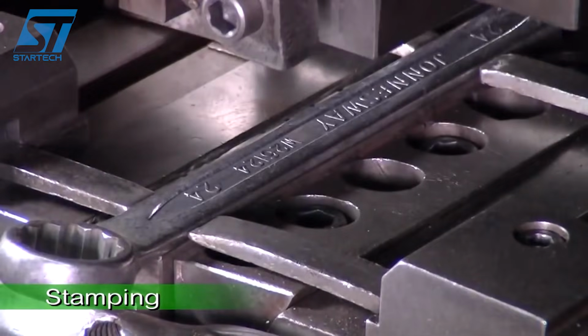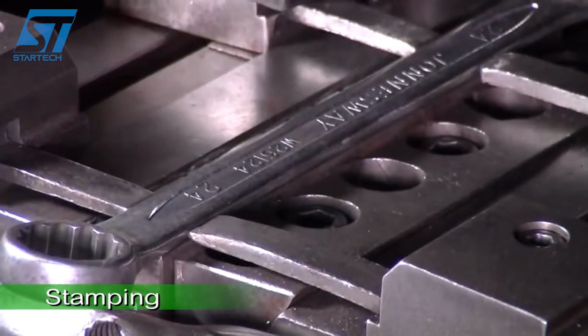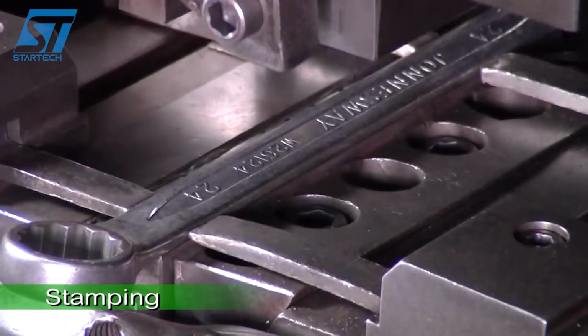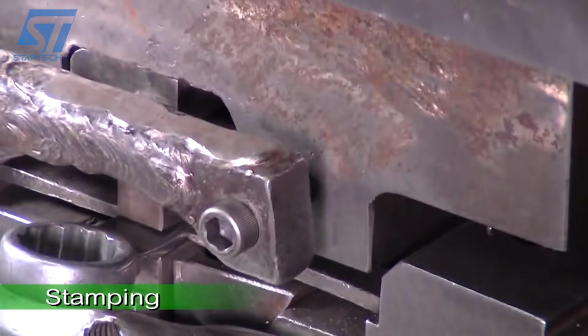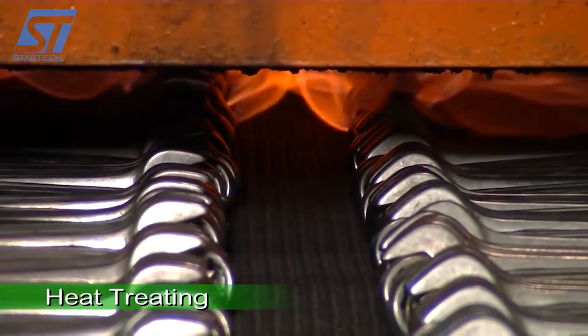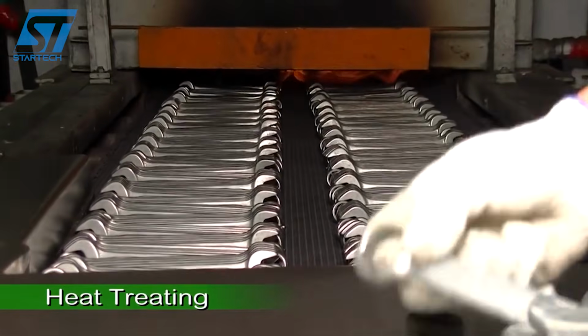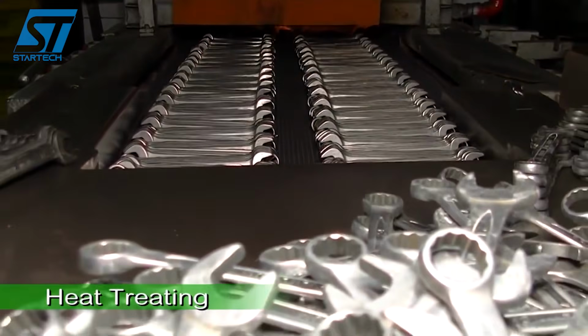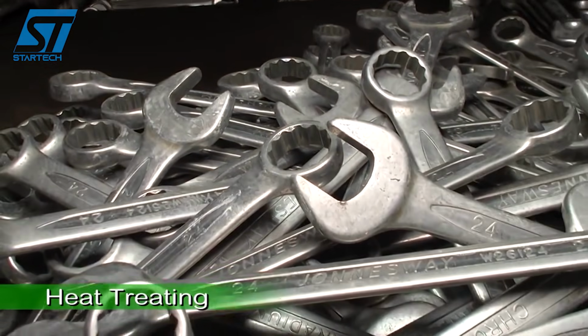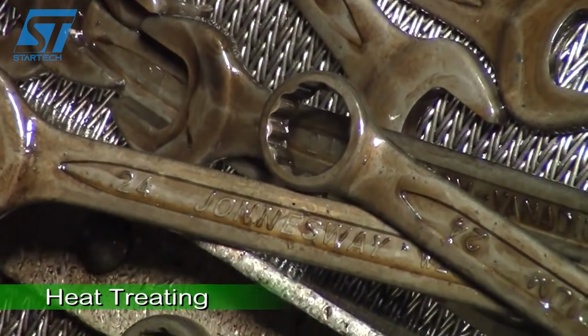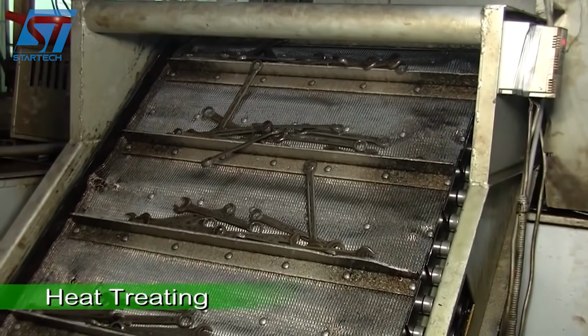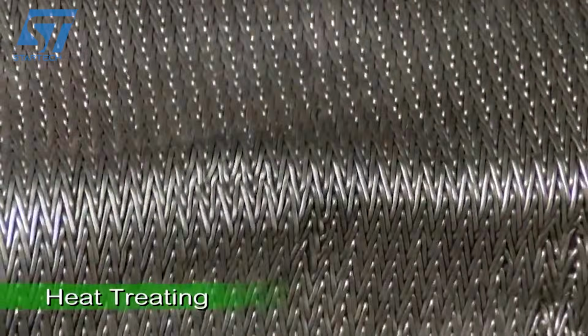Step 3. Heat treatment. This is where science meets metallurgy. The forged wrench blank goes through a two-step heat treatment process. First, quenching, where the steel is rapidly cooled in an oil or water bath after being heated to its austenitizing temperature. This rapid quench transforms the microstructure of the steel into martensite, an extremely hard crystalline phase.